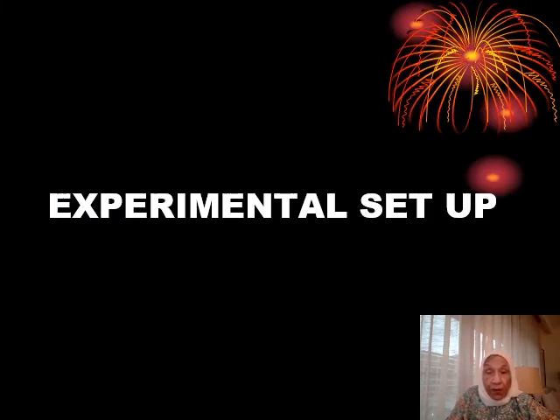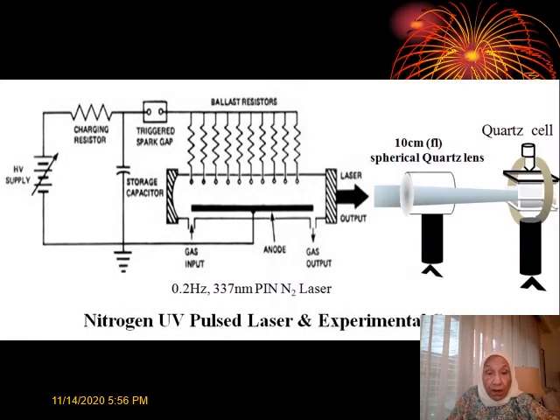The experimental setup used is a nitrogen laser, as seen on the right-hand side. The nitrogen laser produces UV laser light. And then we put the samples of the PN silicon into distilled water, and focus this laser light from the nitrogen laser onto the PN silicon sheets in a quartz cell, immersed in water.